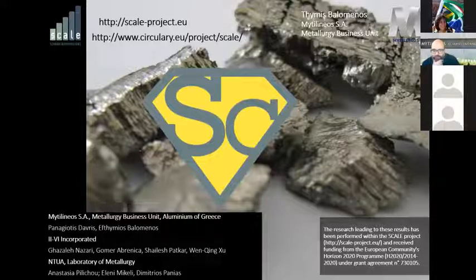That's our current, we're running in parallel different projects, and that's one of them. But we know from the past that when we try to do something simpler, we take out the pig iron and then form mineral wool with the slag. The pig iron production in the electric arc furnace amounted to a pig iron that could be a steel scrap substitute because it had also silicon, titanium, chromium in there. And so it had a fixed selling price as steel scrap. And that amounted to just 30% of the OPEX of the EAF processing.